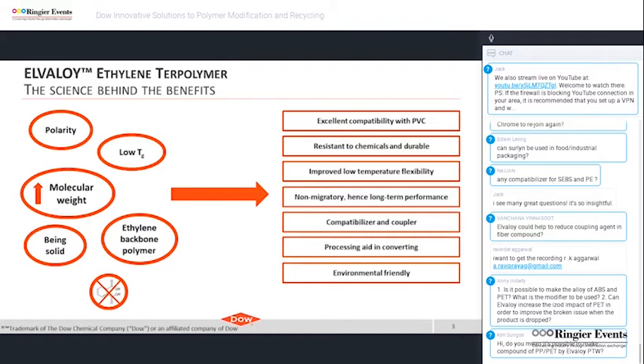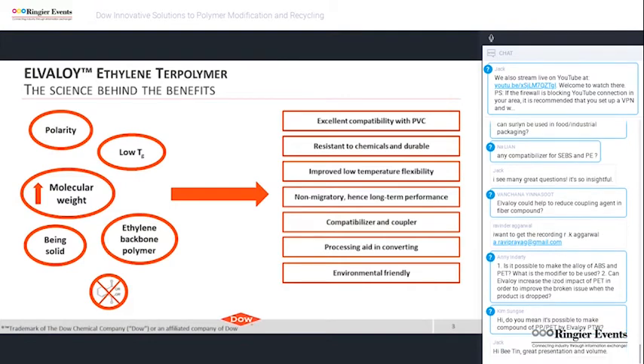Elvaloy ethylene polymer has a different chemistry from Elvaloy AC acrylic copolymer presented in the previous slide by Muthu. Elvaloy polymer is either an ethylene vinyl acetate carbon monoxide copolymer or an ethylene n-butyl acrylate carbon monoxide copolymer. The presence of carbon monoxide monomer increases polarity of alloy polymer and results in excellent compatibility with PVC and other ingredients in the formulation. Elvaloy polymer has a low glass transition temperature of minus 60 degrees,